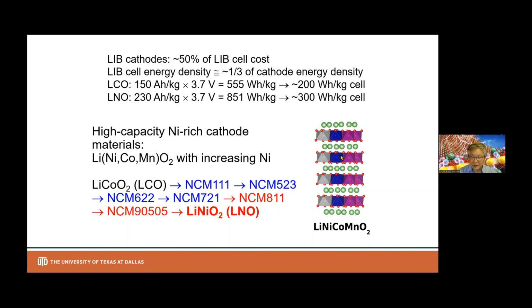We call this layered oxide because of the transition metal in the first generation lithium cobalt oxide. All the transition metal is only cobalt. The cobalt oxide is octahedral bonding. Cobalt oxide is sitting in a metal oxide layer, and then there is an alternating layer of lithium metal. These metal oxide layers are tightly bonded, and the lithium layer is rather loosely bonded, so the lithium ions are going in and out. So that's the intercalation compound.